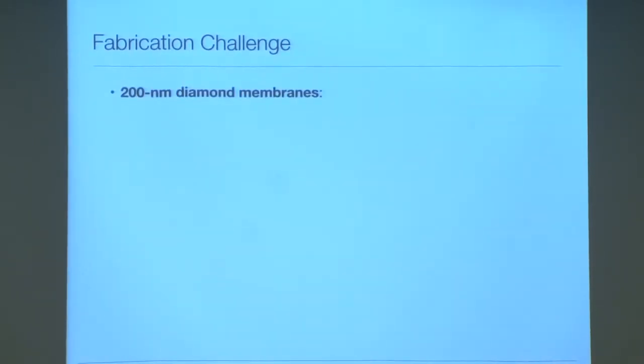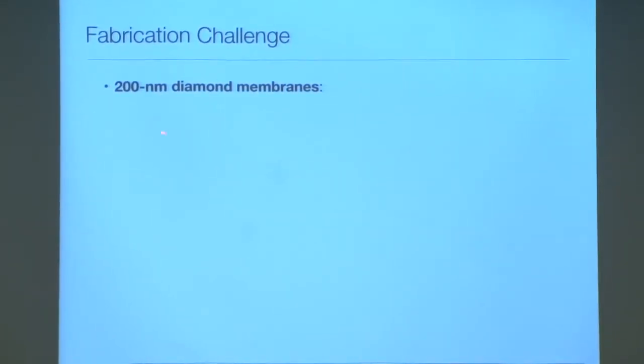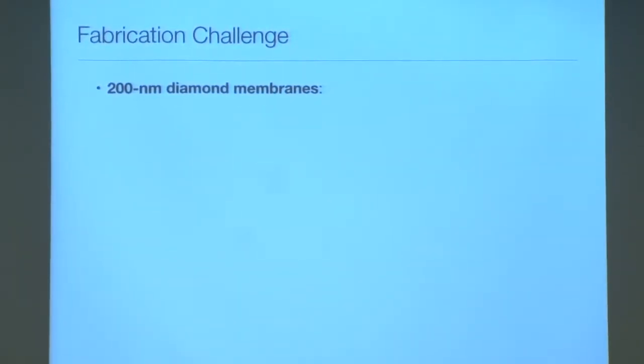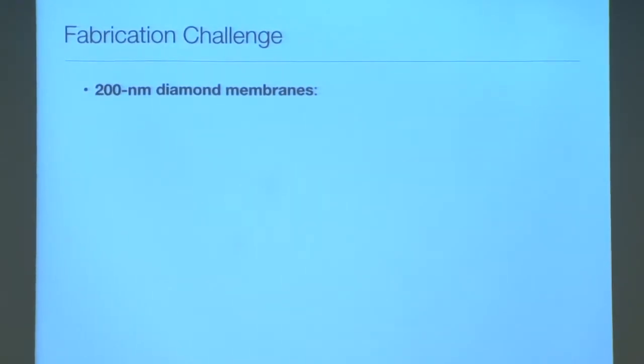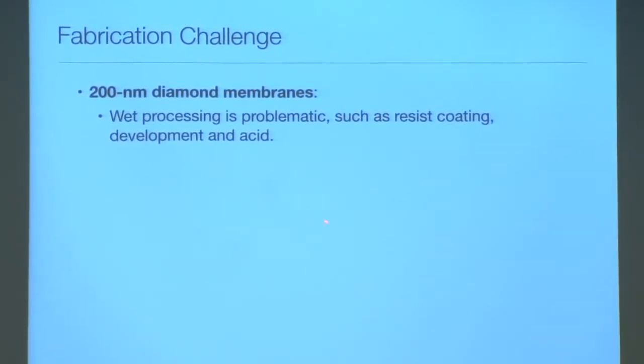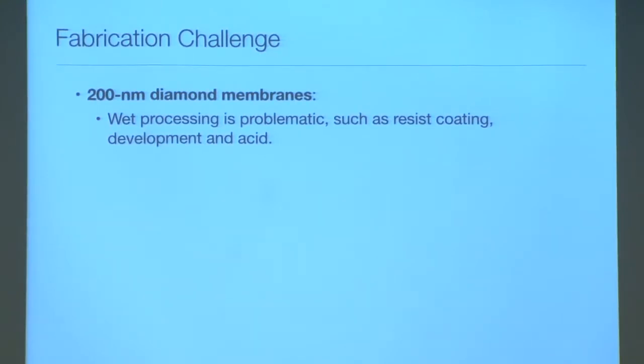It's challenging to pattern on these 200 nanometer diamond membranes with traditional fabrication methods. The first reason is that wet etching would be a problem. If we spin coat these diamond membranes, they may just fly away. And if we put them in a beaker for liquid development, they may just end up somewhere in the beaker and you will never find them again. Also, electron or ion beam irradiation may affect the NV charge state or even damage NVs.